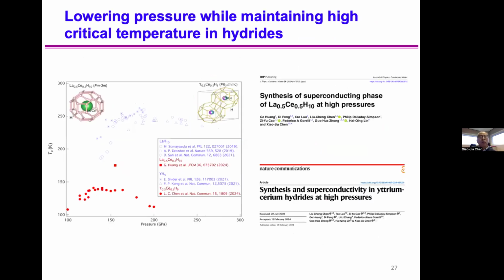Now, since we already determined the TC, we plot here to compare with all the previously published data for lanthanum H10 or yttrium H9. You see the introduction of cerium in lanthanum H10 and YH9. Clearly, the TC remains pretty high, but the pressure is substantially reduced. These are two works we published last year.